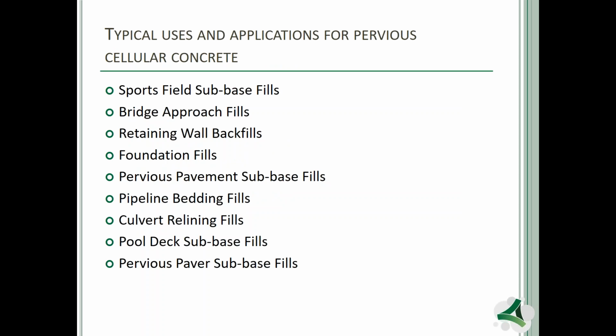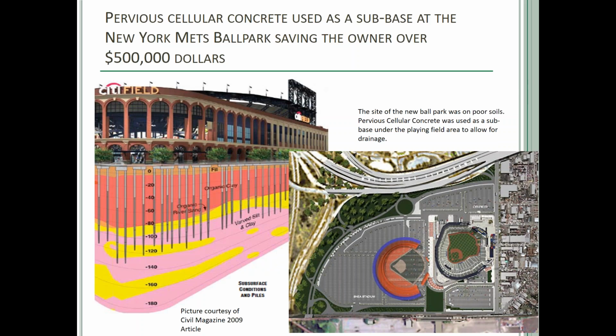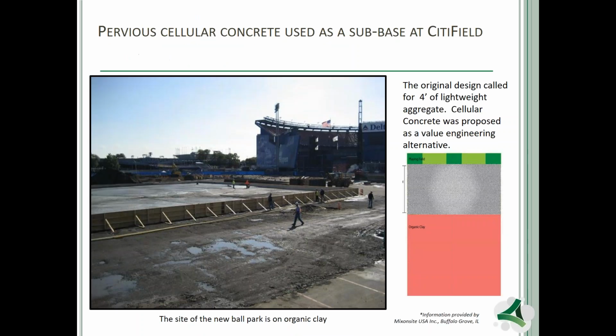Pervious cellular concrete is used in an awful lot of different applications throughout the world. The most famous one would be Citi Field, where the Mets play. And the Mets can never claim a wet ball field for not being able to play a game, because the whole playing field sits on top of 4 feet of pervious cellular concrete, which sits on top of the organic clays, and then the playing field. I always recommend that when you've got native soils over pervious cellular concrete, use a silt fabric to maintain long-term permeability within the project.